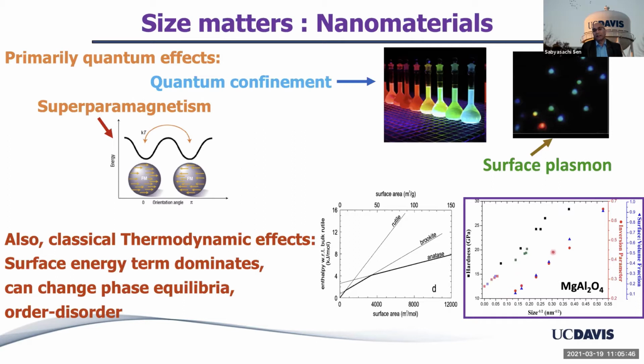And on your right is this plot of magnesium aluminate spinels that came out of my group in collaboration with Professor Ricardo Castro, who made these samples. He showed that the hardness of the spinel nanoparticles increases quite a bit as you lower the size. So this is plotted as a function of inverse square root of size. As size decreases, the hardness increases in this fashion. And then we showed that concomitantly, what changes is the magnesium aluminum order-disorder in spinel sites, which is called inversion. So the tetrahedral, octahedral order-disorder changes following the same trend, and so does the surface to volume ratio. So these are quite interesting properties of materials, solids in the solid state, that come from size.